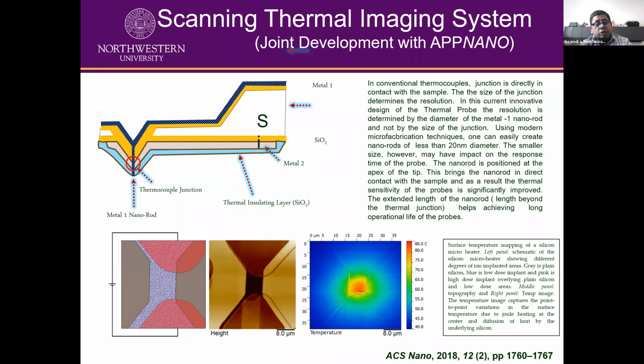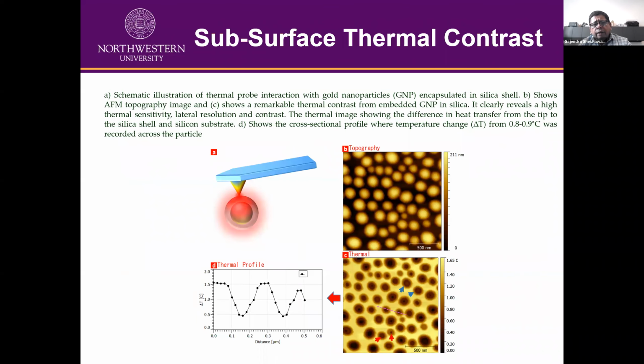You can also heat the probe up to 700 degrees centigrade, and the probe will not bend, or you can heat the sample. Because the thermocouple junction is within the hollow silicon probe, it doesn't bend the cantilever, so you can map high temperatures too. In the figure here, micro heaters with an applied bias heat up, and you can see this thermal probe can easily measure the temperatures. You can look at the publications, which provide the details.